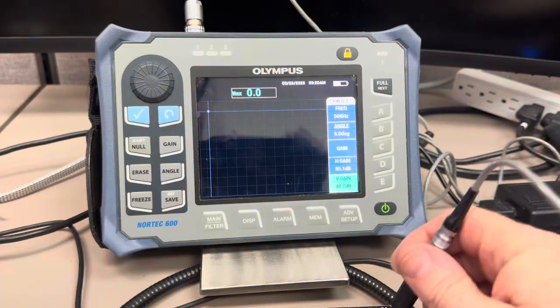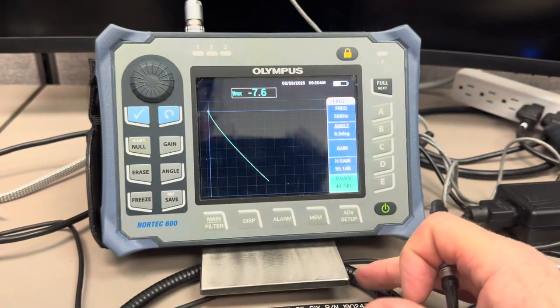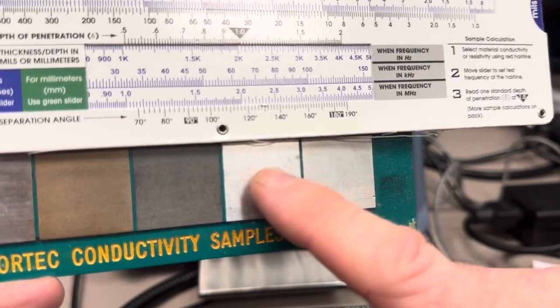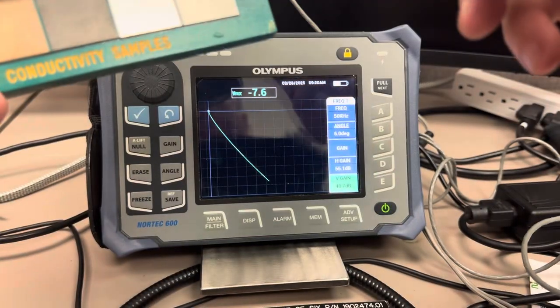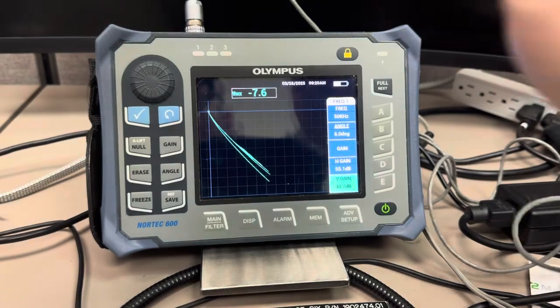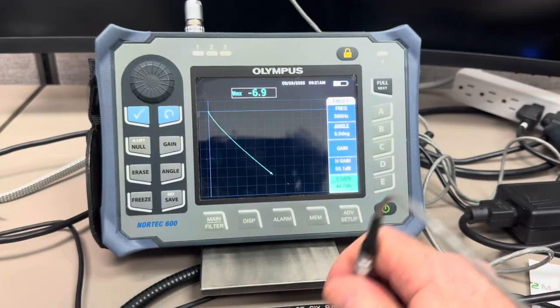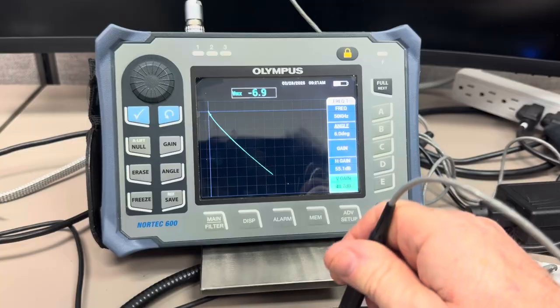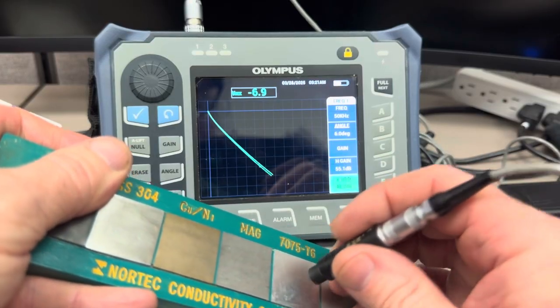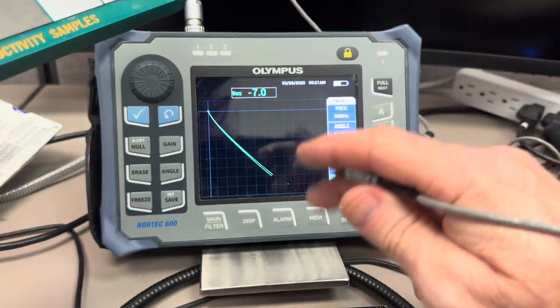All right. We'll try one more. Here we got 7075 T6 on my known sample. Now if I was sorting material and I came to this one and I thought maybe that was 7075 zero. Pretty sure that's what that is. Let's confirm it. It would follow the same line. But it doesn't. Why? I have a mystery material. But you know what? If I go back to my known sample it's actually 7075 T6. See? It's the one right here second from the right. And when I go back on the other sample and hit 7075 T6 it's just going to follow that straight line almost. Right? So that's how you use known samples to set up a calibration conductivity curve. And then you can use the known points to identify other materials.